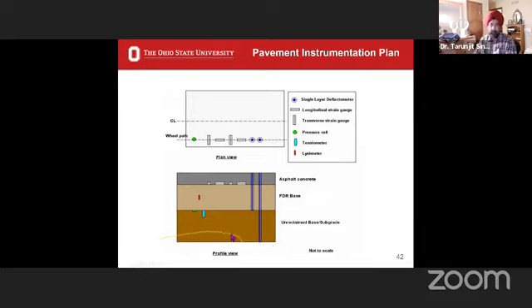So we were looking at, obviously, the compression of different layers, and longitudinal and transverse strains, as we did at the bottom of the asphalt layer. This lysimeter is to collect environmental water quality samples. Because fly ash is in this layer, we wanted to be able to look at what the water quality is of this one. And then we have the pressure coming on the unreclaimed base and then our pore water pressure. So very similar to the previous project, because we'd already done it, we simply extended our knowledge in this case.